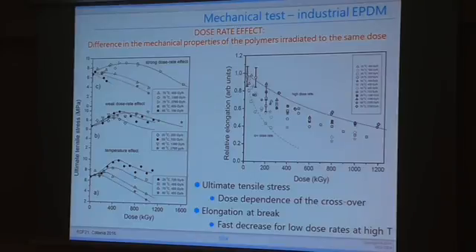So how do we observe dose rate effect on ultimate tensile stress? We observe it as a shift of this crossover as a function of the dose. We can also see that this shift exists for moderate temperatures, but it is even stronger at high temperatures. And also we can observe that if we have the same dose rate but different temperatures, again we can observe a shift of the crossover, in a way that an increase of temperature will shift it toward lower doses.